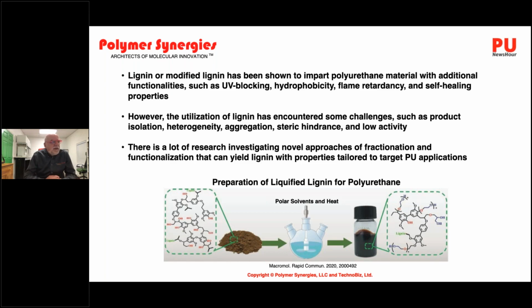Lignin has been used in polyurethanes for a while in a lot of different applications. It's very good for UV blocking. It's very good for providing hydrophobicity. It's also very good for flame retardancy because it chars. And it's also used in self-healing polymers. So if it's used in a solid state, incorporated in a polyurethane, like a polyurethane adhesive, it could be used as a self-healing component, where if we get a crack in the polyurethane coating or adhesive or an elastomer, it can remend itself, and that's due to this polyhydroxy functionality of the lignin.